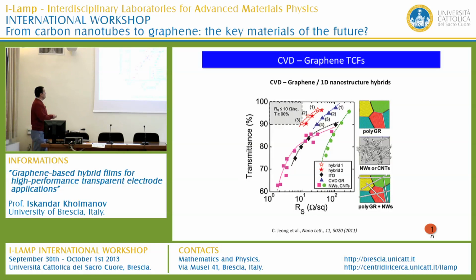So there were recent publications in Nature and Nano Letters that showed the integration of graphene, polycrystalline graphene, with one-dimensional nanostructures is a promising approach to decrease the effect of line defects like graphene grain boundaries. Because when you put nanowires or carbon nanotubes, you can cross the line defects and can bridge the different graphene domains, and in this way you can eliminate or decrease the effect of line defects. They showed that in this way one can obtain sheet resistance lower than 10 ohm per square.